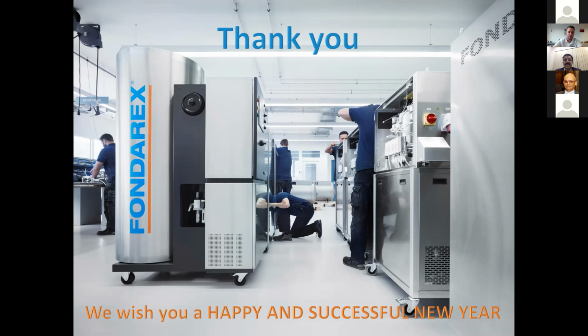It's just how precisely the die maker cuts the groove, and then the seal has to sit nicely in the groove. Behind the sliding core, the seal doesn't need to stand out much, maybe 0.3 millimeters, and it's always a little bit under pressure. That's all. I don't think we can do much more. I have even seen very big dies with two seals, an inner seal and an outer seal, but in the end I cannot say how much better it was.